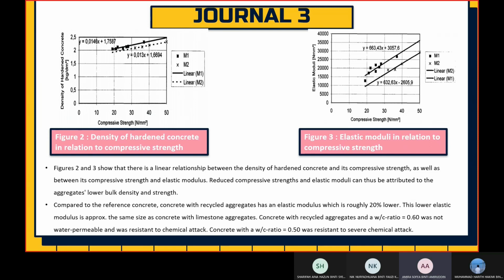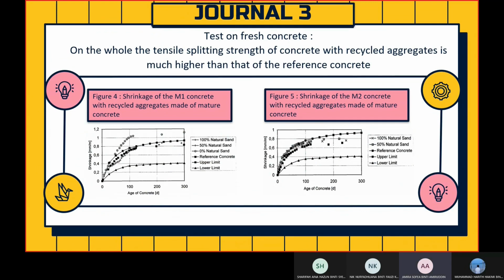Concrete with recycled aggregates and a water-cement ratio of 0.6 was not water permeable and was resistant to chemical attack. Concrete with the water-cement ratio of 0.5 was resistant to severe chemical attack. The findings of the tests on fresh concretes show that, on the whole, the tensile splitting strength of concrete with recycled aggregates is much higher than that of the reference concrete.